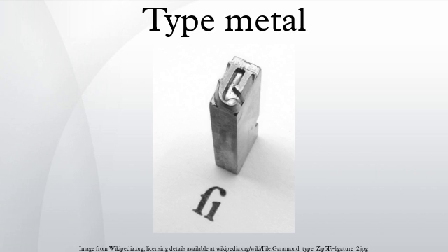Alchemists had shown that when stibnite, an antimony sulfide ore, was heated with scrap iron, metallic antimony was produced. The type founder would typically introduce powdered stibnite and horseshoe nails into his crucible to melt lead, tin and antimony into type metal. Both the iron and the sulfides would be rejected in the process. The addition of antimony conferred the much-needed improvements in the properties of hardness, wear resistance and especially, the sharpness of reproduction of the type design, given that it has the curious property of diminishing the shrinkage of the alloy upon solidification.